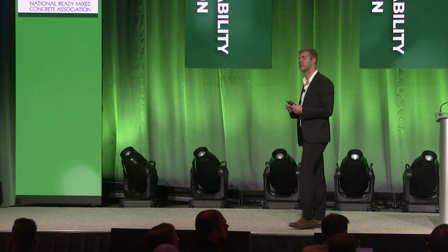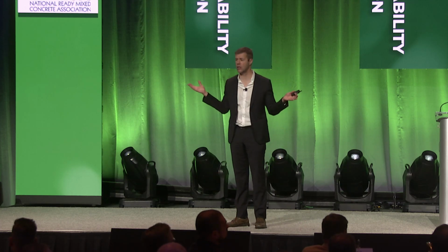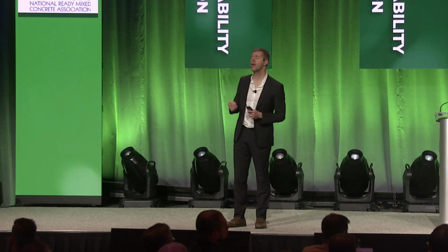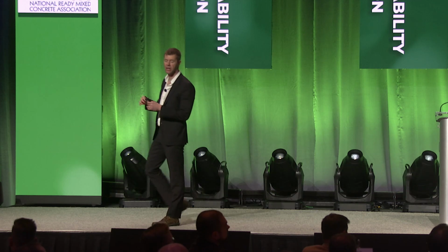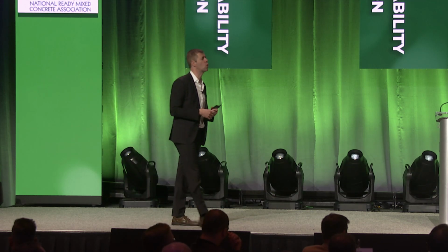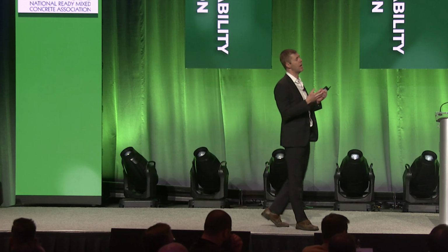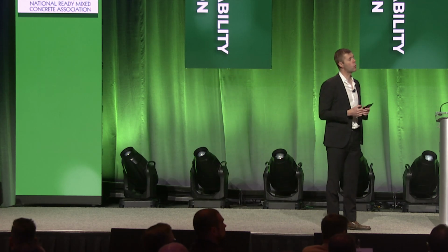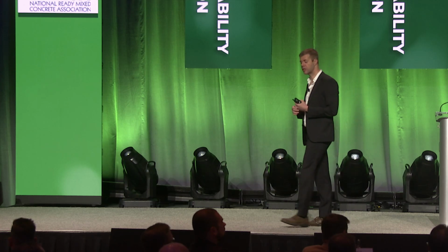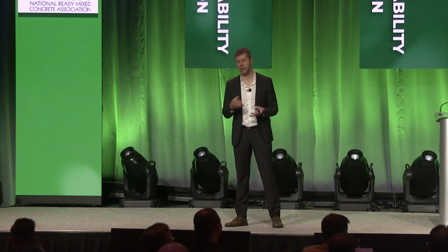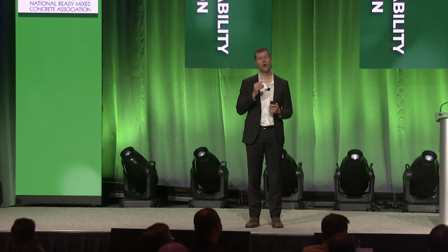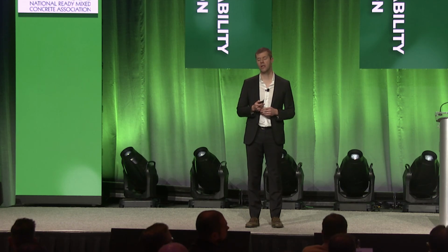Upper left-hand corner, deficient amount of fine sand, it kind of just disintegrates and falls apart. Upper right-hand corner, too much fine sand. It's stiff, too much surface area. Lower left-hand corner, high amounts of intermediate. Okay, it's kind of stiff. Lower right-hand corner, high amounts of coarse aggregate. Oh my God, it's segregating, it's coming apart. And the one in the middle, that's just right. That's the mix that got it just right in the middle.